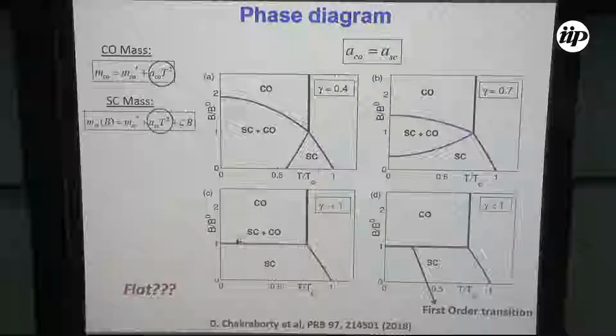So for weak enough coupling, what we can see is that we will have superconductivity at low field, we will have charge order at high field, but we will also have a significant region in the phase diagram where we will see that there is a coexistence phase. If we look at it carefully, even at B equal to 0, we can have a coexistence phase. But in experiments, what we saw is that we need an onset field to get the charge order. So let's increase the coupling between the two fields.